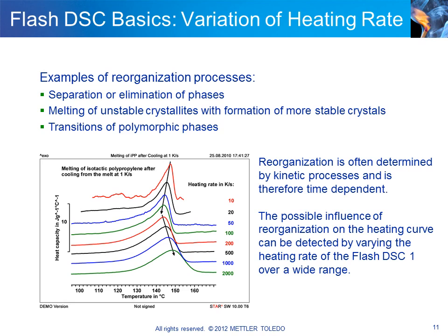Reorganization processes can be investigated by varying the heating rate, or even completely suppressed by choosing suitable heating rates. If reorganization occurs, the structure of a material changes during heating. Examples of reorganization processes are phase separation with mixtures or the separation of certain phases in alloys. In the case of polymers, small unstable crystallites first melt and then recrystallize on further heating to form more stable crystallites. The transitions of different metastable polymorphic phases are also reorganization processes that depend on the heating rate.